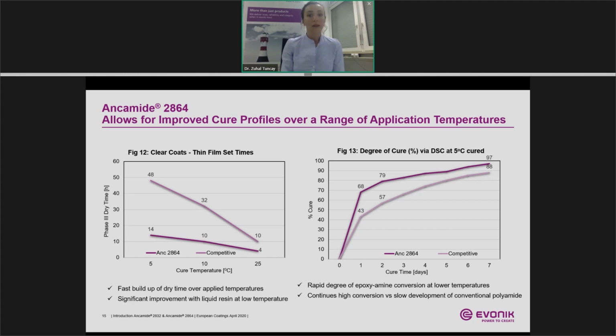Moving to figure 13. The degree of cure is obtained here using DSC, cured at 5 degrees. What we see here, 2864 on day 1 achieved almost 70% curing degree, and after 7 days, 97%. And the competitive curing agent reached on day 1, 43% curing, and after 7 days, 88%. These results demonstrate clearly the rapid development of the network for 2864 at early stages of curing for low temperature curing. And in this case, it closed the performance gaps for the low temperature curing for polyamide systems.